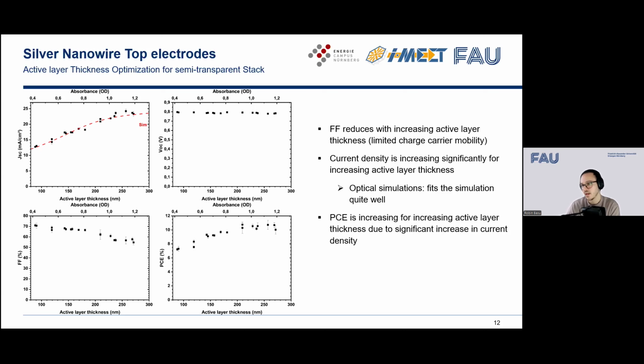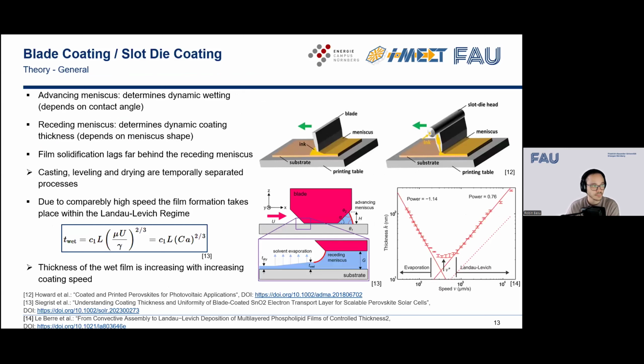And we can achieve very high JSCs of more than 23 milliamps in a semi-transparent device, while maintaining comparably high fill factors of more than 60 for those thicknesses. And that allowed us to get quite close to 12% in a semi-transparent device. This is again 0.1 square centimeter cells, and the average, of course, given with error bars.